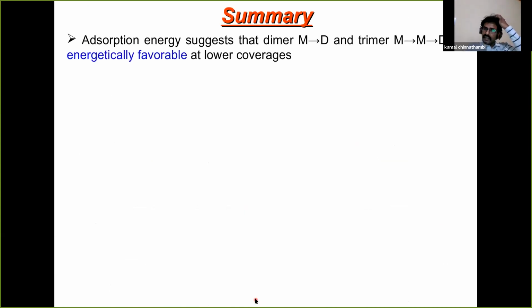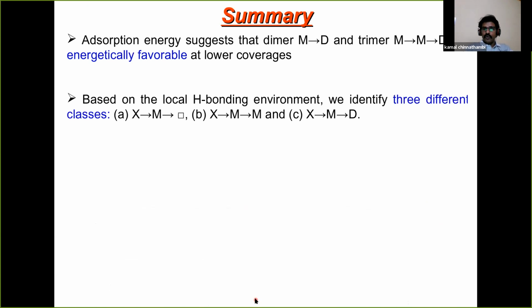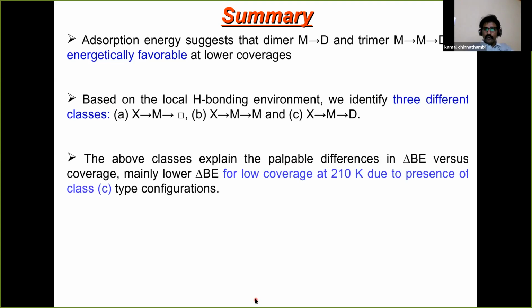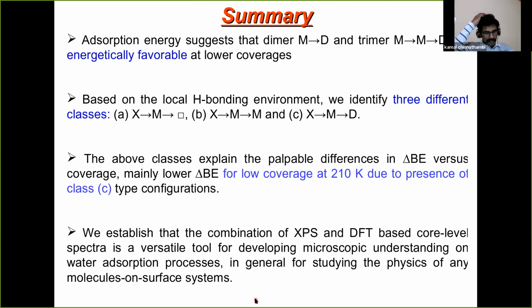From our calculations, we find that whenever we have a dissociated molecule as an acceptor to the hydrogen bonding, we have an energetically favorable situation, especially at lower coverages. Using our structural model, we could classify 3 different classes based on the acceptors. So we could explain the lower coverage at 210 degree, where there are very low values of binding energy, because it contains a lot of dimers or trimers from class 3, which has dissociated molecules.